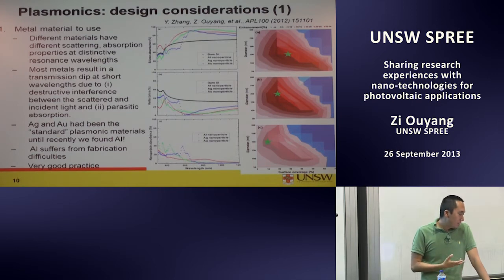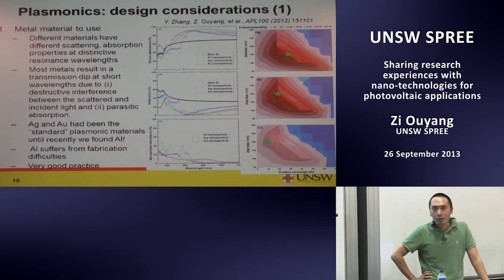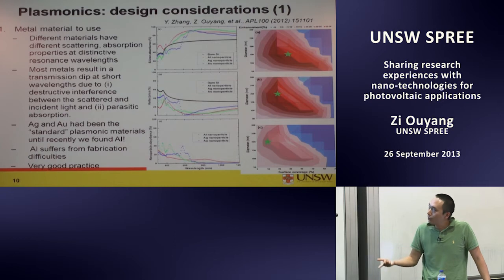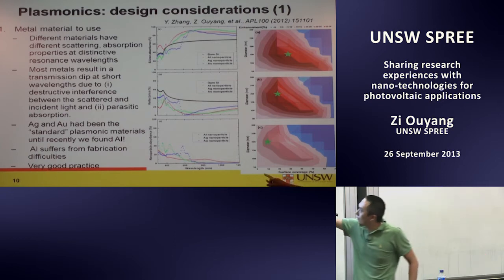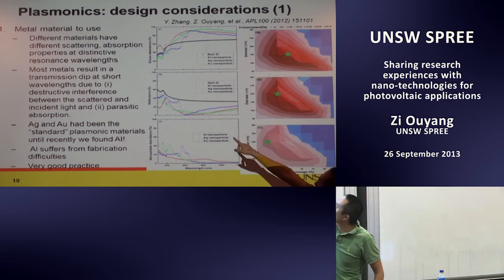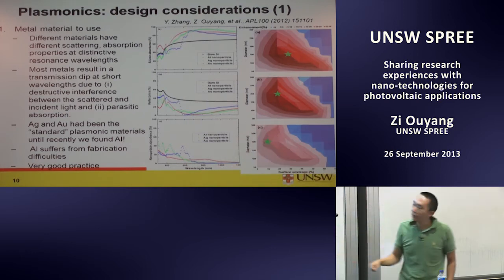Before we started this work, we thought, based on the literature, that gold and silver were the standard plasmonic materials, until we found aluminum is way better than them. They have less absorption, less reflectance. So if you look, the red one is the aluminum one.